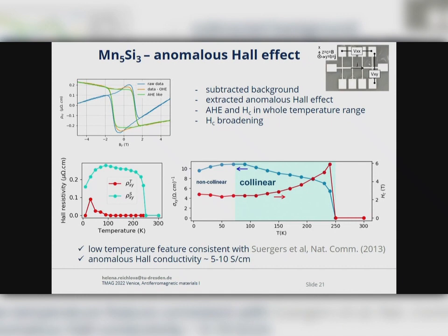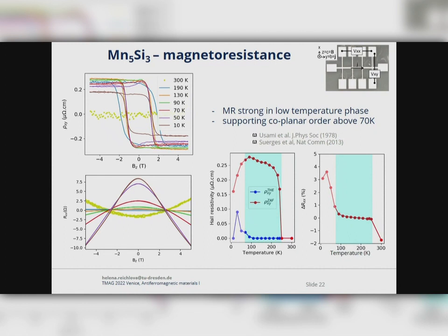So here, all good, it seems that we are fine, but what is very interesting and important is that all the signal is actually dominated by this robust, clear, anomalous, spontaneous part, which I plot here, which seems to be independent of the first magnetic phase transition and is completely absent in the paramagnetic phase. Here I just plot the calculated anomalous Hall conductivity, which is approximately 5 to 10 Siemens per centimeter, and also the coercive field, which is usually some sort of indication of a transition, but in our case it remains constant in the full temperature range when the sample is magnetically ordered. We also detect simultaneously the magnetoresistance, which, like this rho XXT, is present only in this non-collinear phase and is basically absent in the collinear phase where we look.